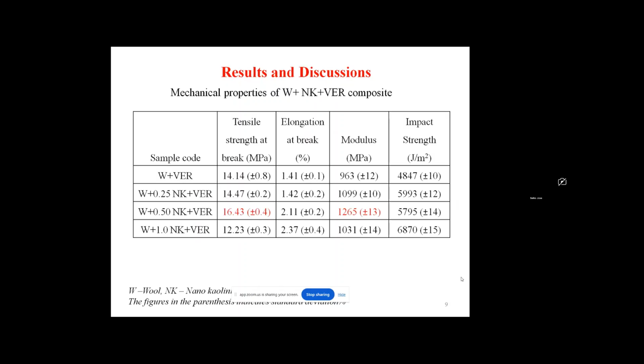Coming to the results and discussion, here W means wool fabric, NK means nano kaolinite, and VER means vinyl ester resin. We tried three different combinations along with the control sample. Here you can see 0.5% nano kaolinite gives the highest tensile strength, 16.43 megapascal. The modulus was also found to be higher, around 1265. Out of the three different combinations, 0.25, 0.5, and 1% of nano kaolinite added to the vinyl ester resin, we found that 0.5% of nano kaolinite gives the best result.